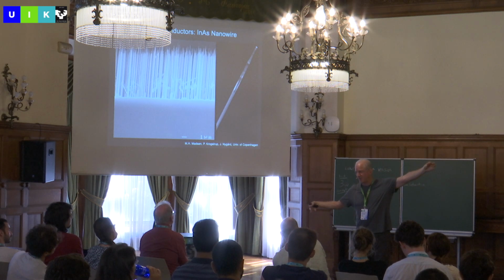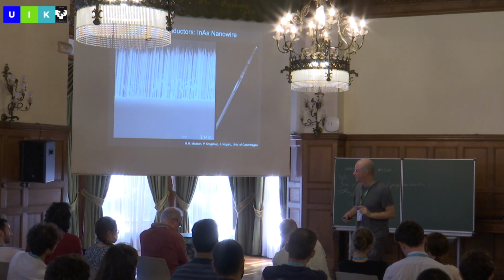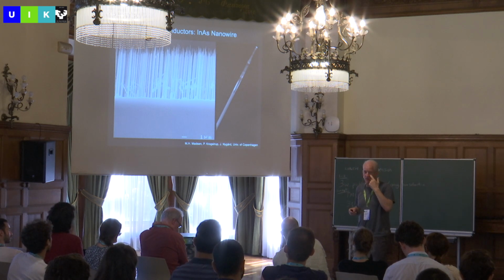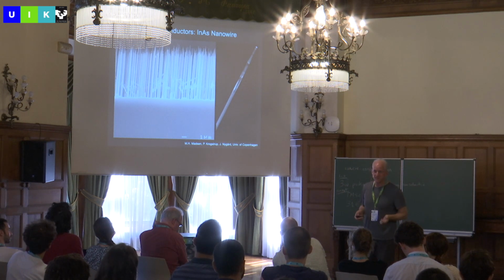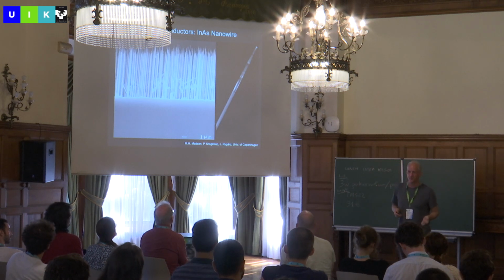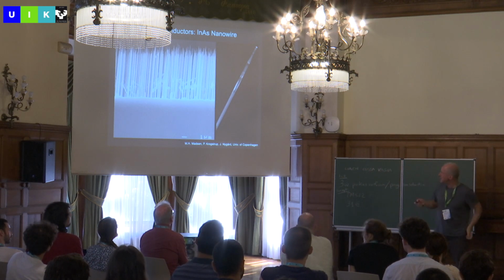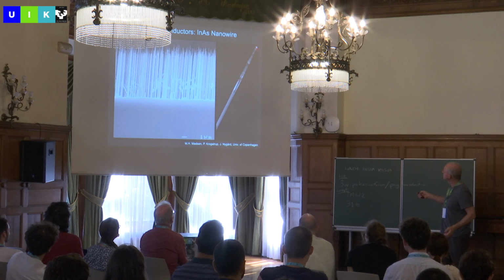So it's like a free motion in one direction and quantized out in the other two motions. And this is the way that these nanowires were grown. It's a remarkable process. If you don't know about this way of growing nanowires, you can see at the end of the wire, there's a little gold ball.